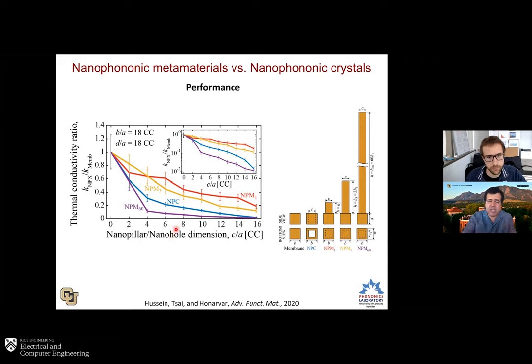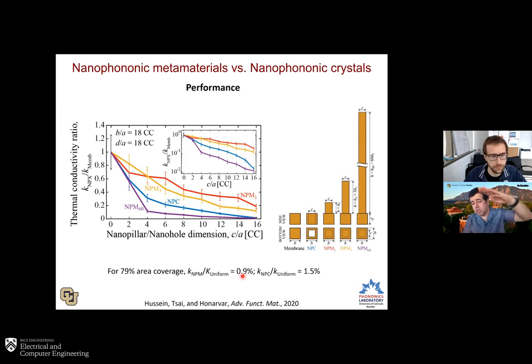And in fact, you can see that for an area coverage of roughly 79%, with an NPM, we get 0.9% thermal conductivity compared to the base membrane, whereas for the phononic crystal, 1.5%. And if you look at that green line, for the same thermal conductivity reduction, you can actually achieve this with an NPM if you go to the left with a much lower coverage. So that was a study that we've done.